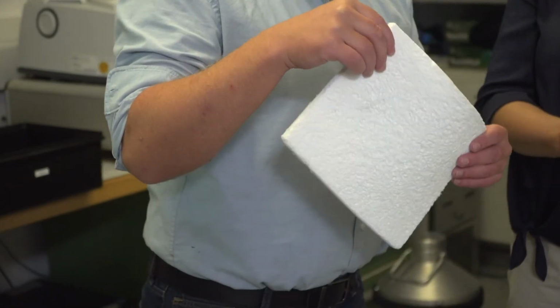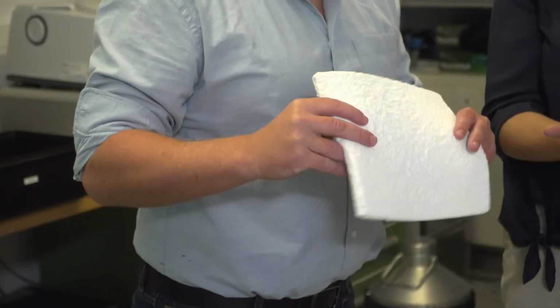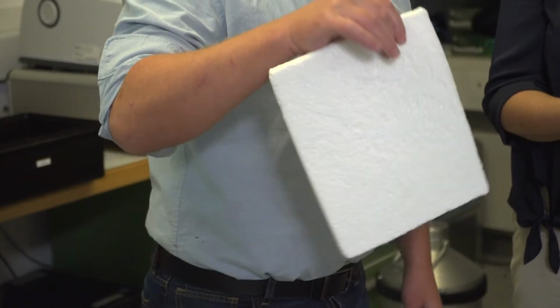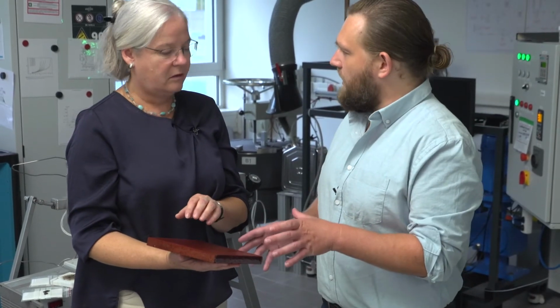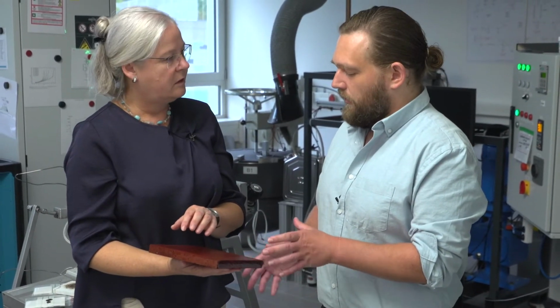These are our organic aerogels. For sure, they are not as high-temperature stable as the silica ones, but in many cases you do not need these high temperatures. And this material is really good because you can process it without supercritical drying. So this is like the traditional RF aerogel, originally from Lawrence Livermore chemistry? Yes, it is a resorcinol formaldehyde polycondensation, and we make tiles with that, and we make particles, and we do a lot of things with this material.